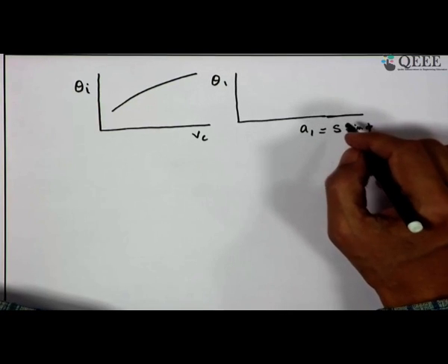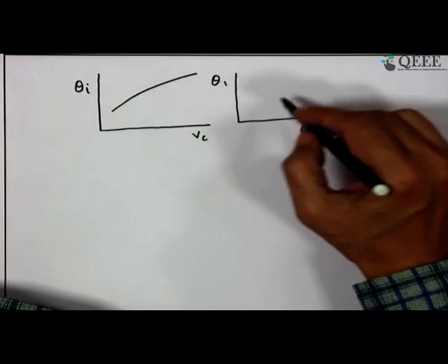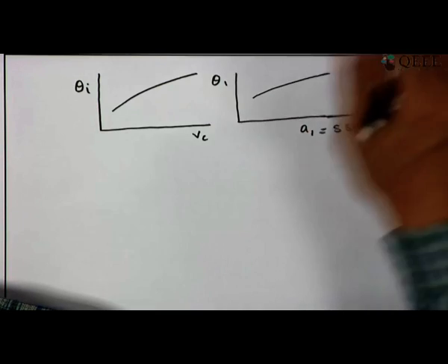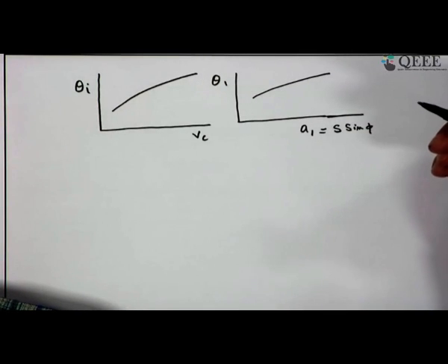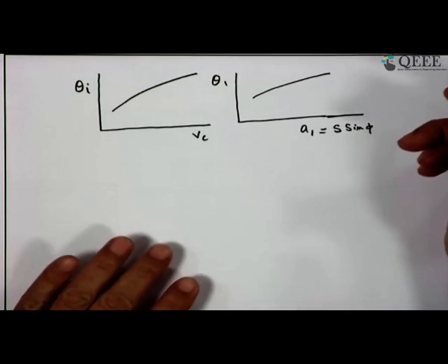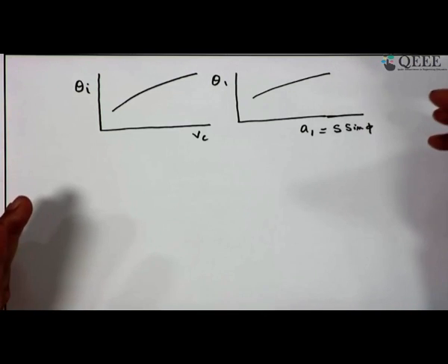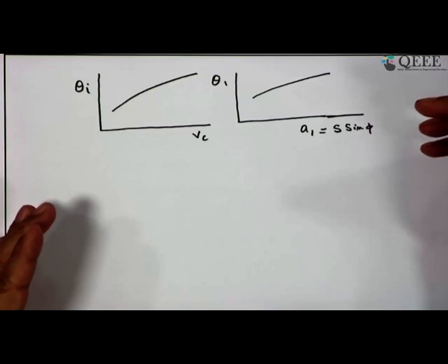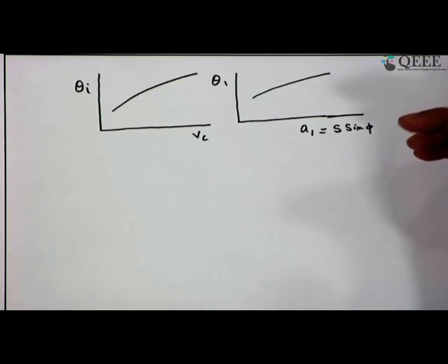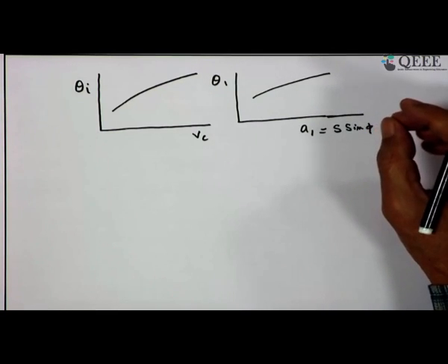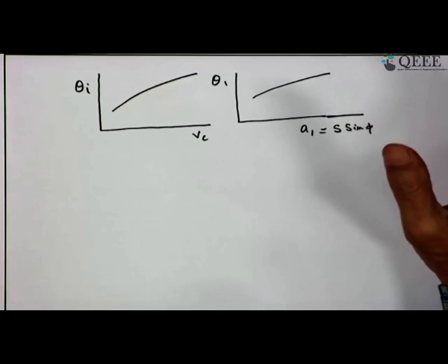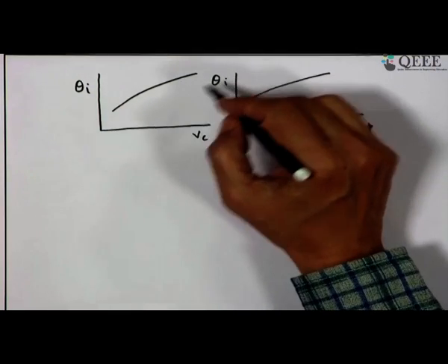So it is S sin phi, and that also follows this relation, and this is what you achieve experimentally. You independently use a work tool thermocouple, a very convenient way to measure the interfacial temperature. It is an average one, and if you measure with a properly calibrated work tool thermocouple, you can have a plot like this.